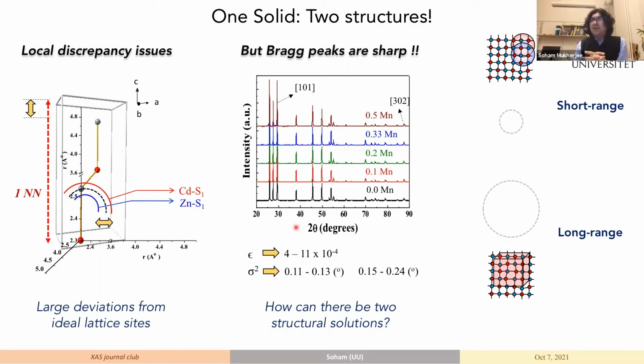So there is something going on at the very local length scale, which is not captured when you do a volume averaging of the structure at the length scale of 50, 60 angstrom, which is typically what we do in X-ray diffraction. Okay, so you're saying there's not a lot of strains evidenced for length scales larger than 50 or 60 angstroms, so it has to all be healed more quickly. Yes. And this is exactly what the second part of the talk will show.